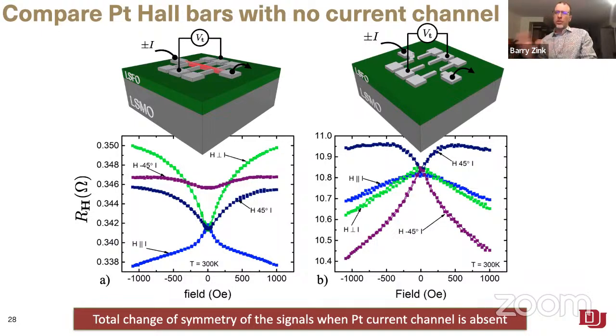A lot of the really interesting stuff happens at lower temperatures where the electrons are starting to freeze out. One thing that's been frustrating for me is that the carrier density is not so high, and that tends to be very sensitive to the directions and anisotropies. This looks exactly like gallium manganese arsenide type of weird things that used to happen. Yeah. And for example, there's work on the planar Hall effect in LSMO, with large effects. It does a lot of the same stuff that gallium manganese arsenide does in terms of picking up strange magnetic anisotropies, and so there can be in-plane anisotropies. There's a lot of stuff in the LSMO that can be complicated, which is why I was hoping we could not be so strongly affected by the LSMO, but that is an unfortunate consequence of reality: we are having to sort out what's happening in the LSMO.